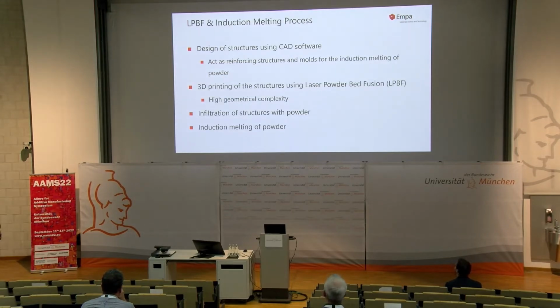What we try to exploit using laser powder bed fusion is geometrical freedom, which gives us the opportunity to design complex structures with lower processing time and with only one processing step. So the idea here is to design structures which will play a dual role. The first role is to be the reinforcing phase of the composite material, and secondly, to play the role of a mold, inside of which we will later on infiltrate the powder, and this powder will be melted using induction melting.